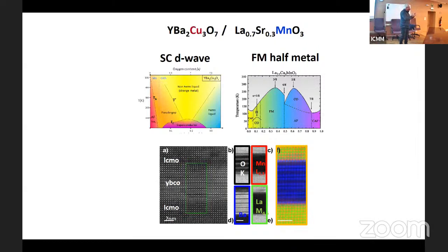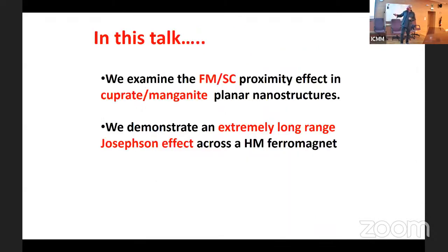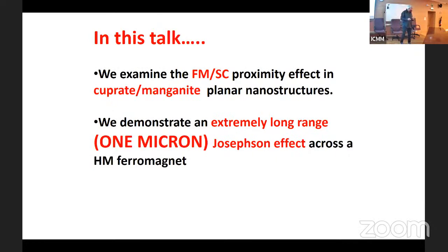And you can bring together competing or very different ground states, like, for example, in this case, a superconductor and a ferromagnet, a half-metallic ferromagnet. And this is what this talk is about today. So we want to examine the ferromagnetic superconducting proximity effect in a cuprate manganite nanostructure, and we want to demonstrate an extremely long-range Josephson coupling between the two superconductors across a half-metallic ferromagnet. And when I say extremely long range, it means really, really long. It means a 1 micron length scale at relatively high temperatures, right?